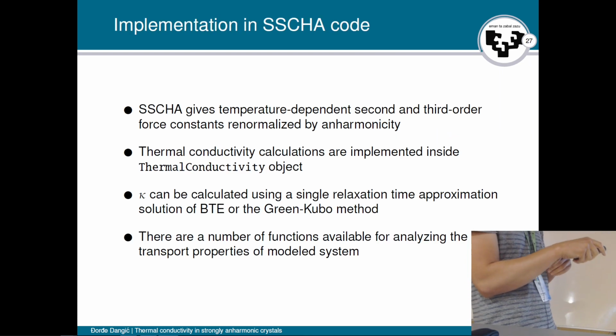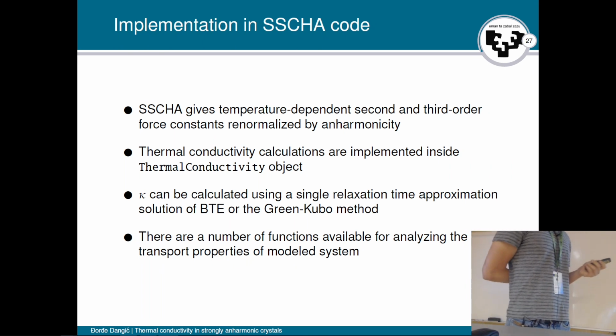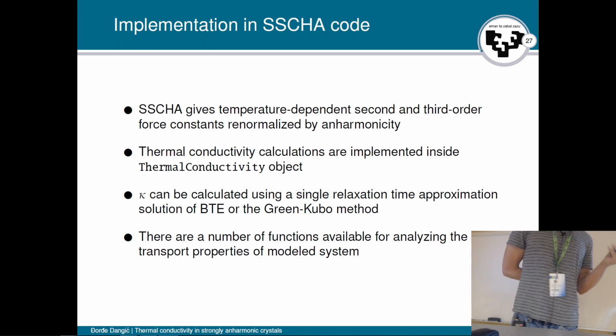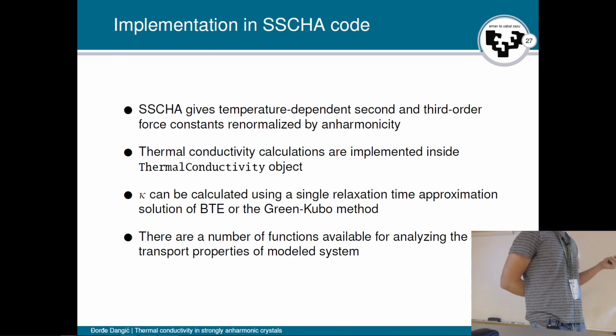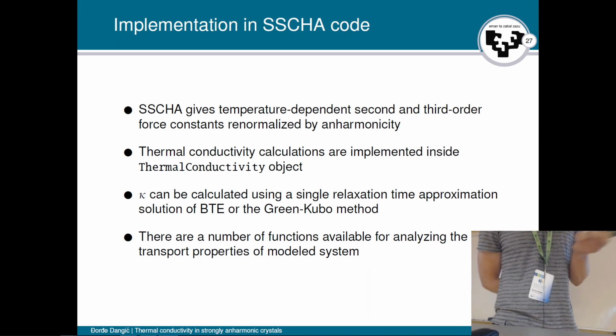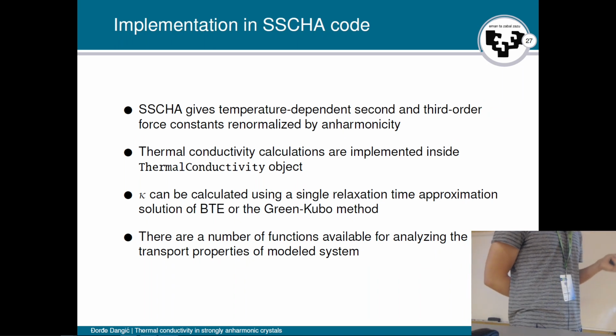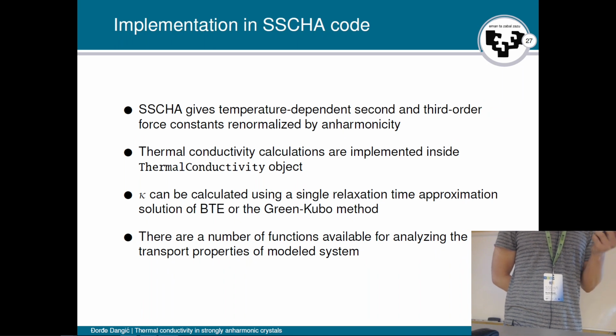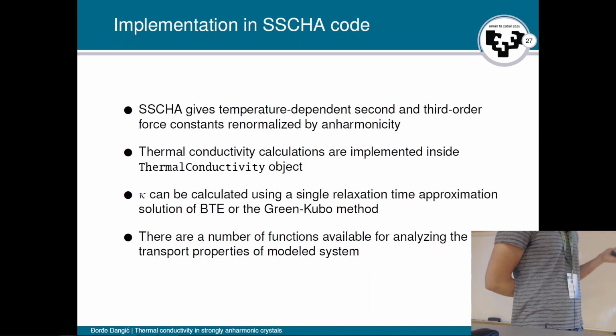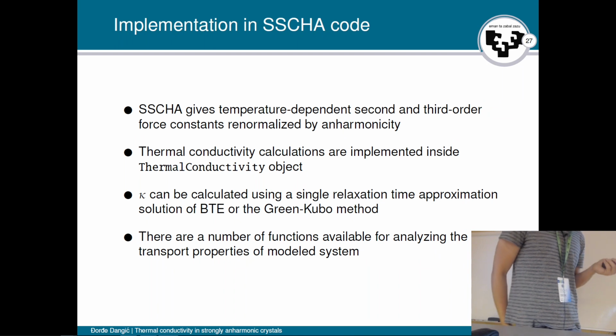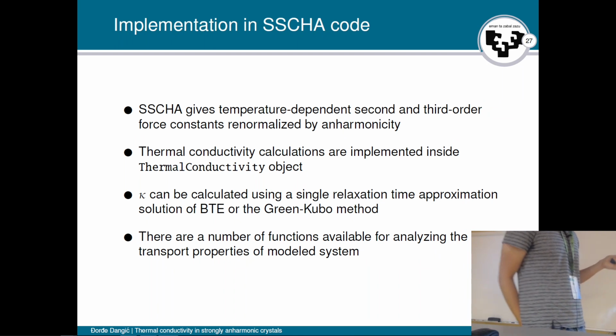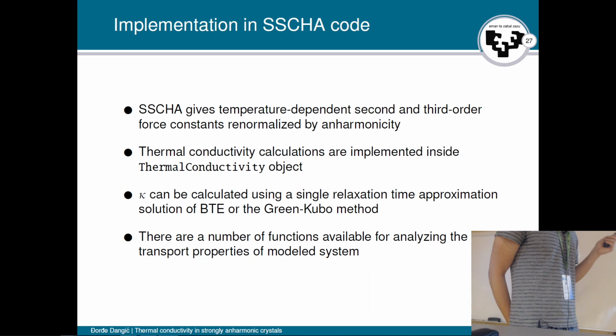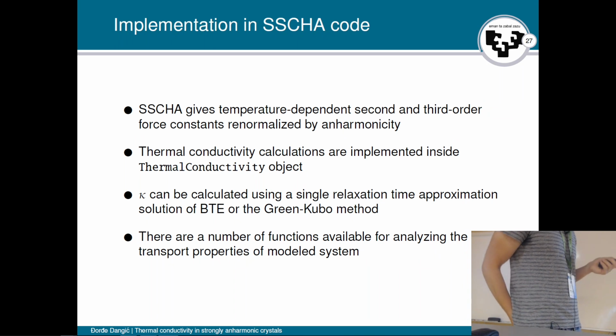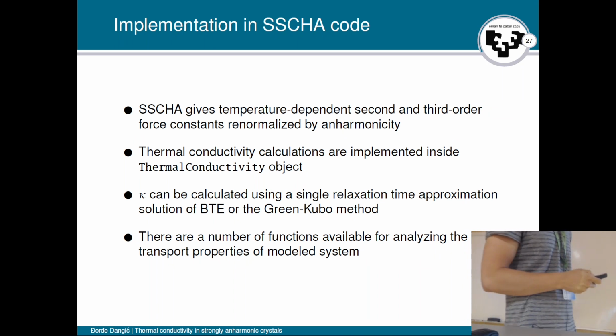Well, the SSCHA gives temperature-dependent second and third order force constants, which are renormalized by the anharmonicity, which usually means that they are much easier and much more suitable for this type of calculation, because in my experience, once you use SSCHA, you get more short-range interaction. So your Fourier interpolation works much better in SSCHA and other non-perturbative methods than if you just calculate it from the analytical type of approach to force constants.